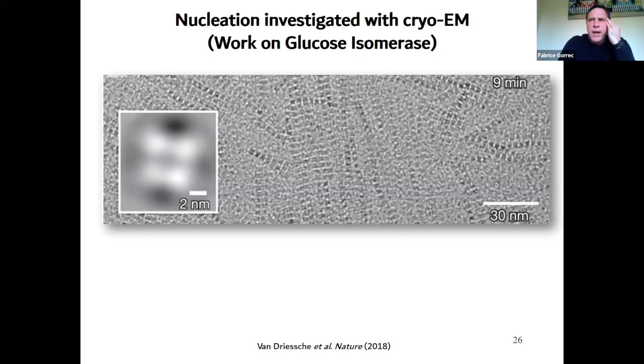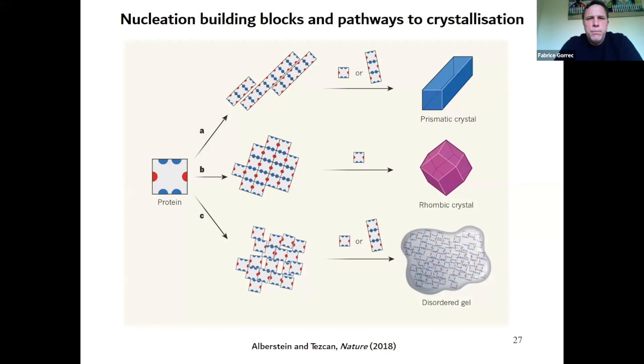So after that, what's happening is you have what they call building blocks in these 2D. This is 2D based on glucose isomerase. So according to different associations of these building blocks, you may have different crystals at the end, or something else like a disordered gel. So basically, what I wanted to say about that is that it's interesting to see that there's already a kind of high degree of order straight away, and that the pathway to crystallization is established very early.